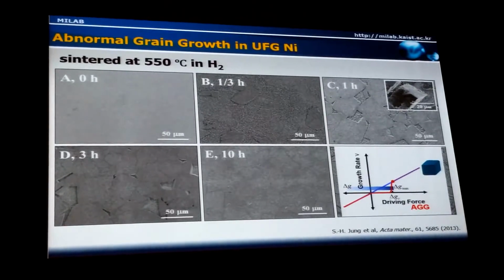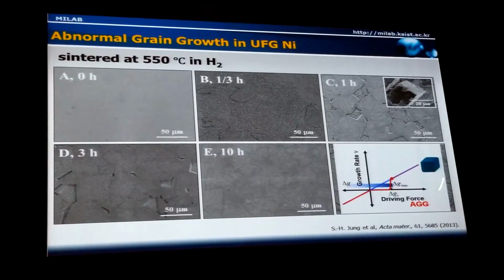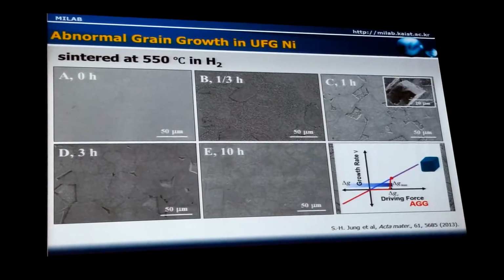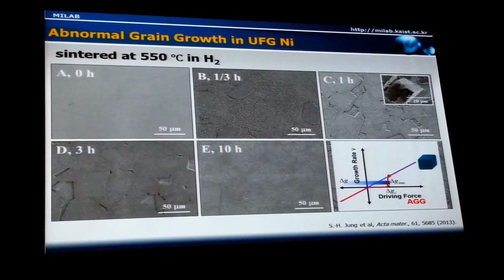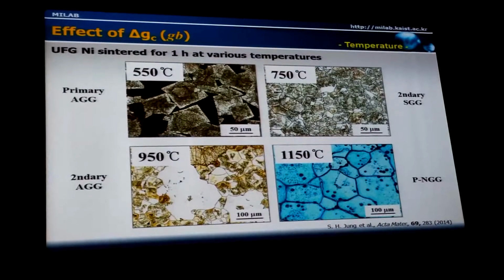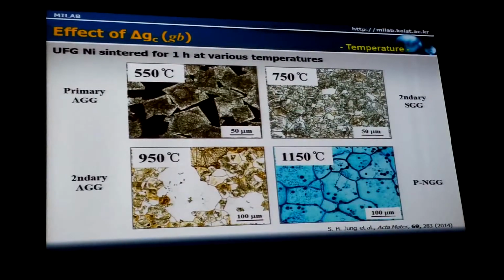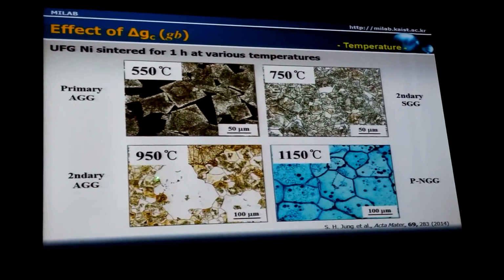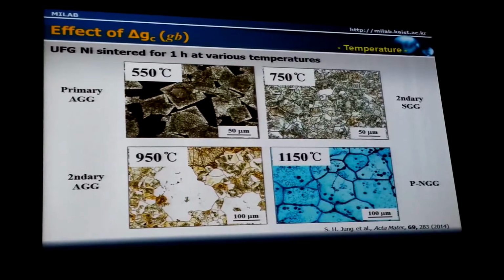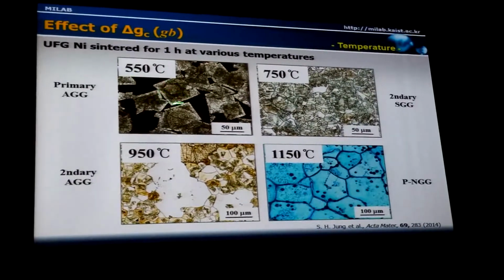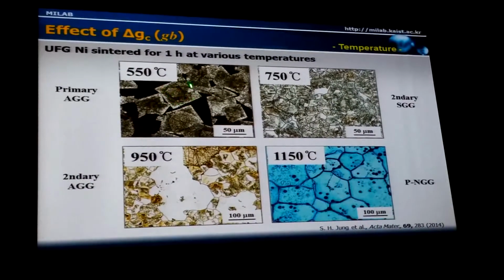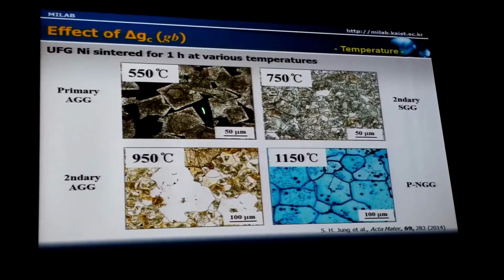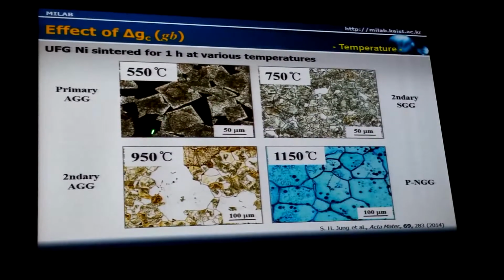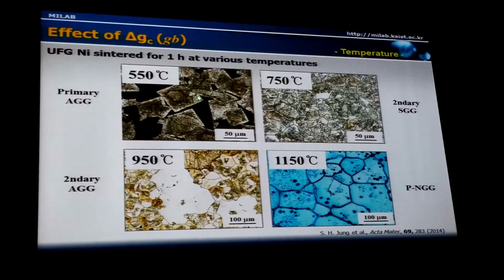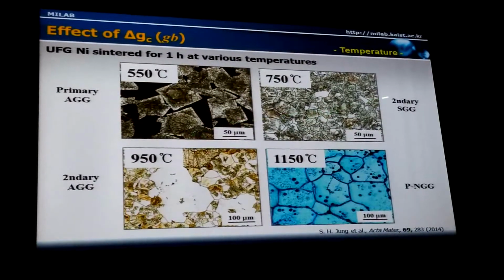This observation can be explained well by the nonlinear behavior of the boundary migration. We prepared samples at different temperatures: 550, 750, 950, 1150. At 550, abnormal grains formed, and this is an abnormal grain. The black area is the fine 180 nanometer matrix. And at 750, these abnormal grains impinge upon each other.